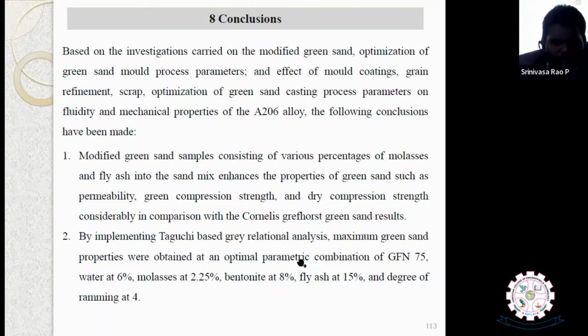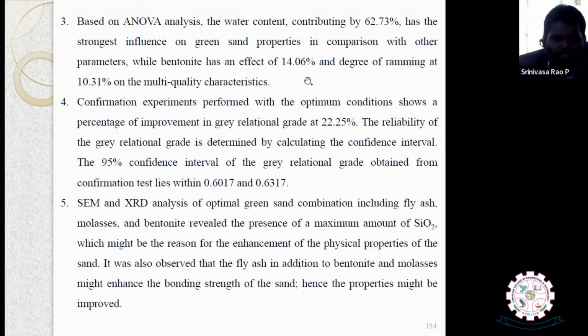Taguchi-based analysis also reveals the optimal parametric combination: 75 GFN, water percentage 6%, molasses 2.25, bentonite 8, fly ash 15%, and degree of ramming 4. By ANOVA analysis, water contributes 62.73%, and bentonite has an effect of 14.06%, followed by the degree of ramming. Confirmation experiments, SEM and XRD analysis found the maximum amount of silicon oxide, which is the reason for the enhancement of the physical properties of the sand.